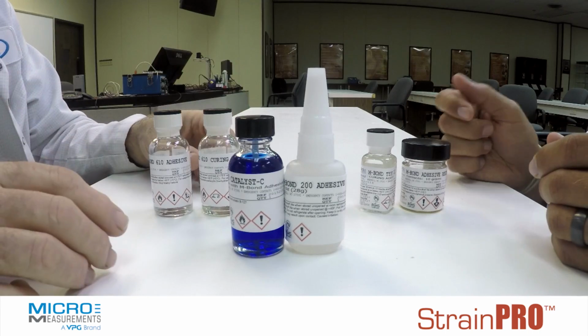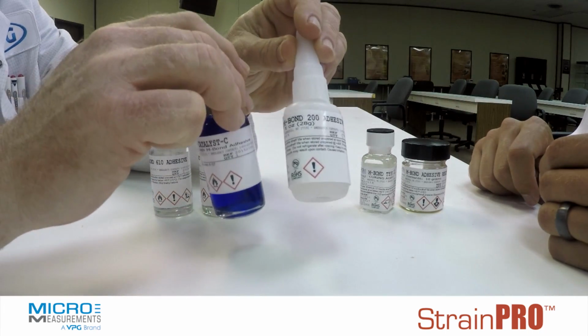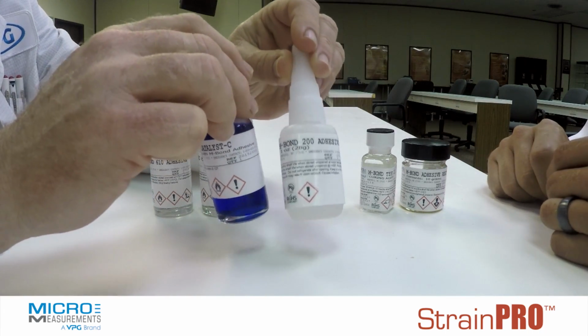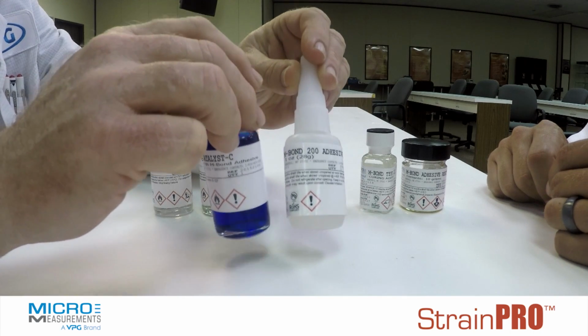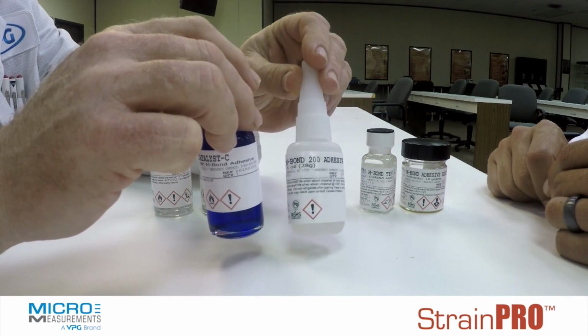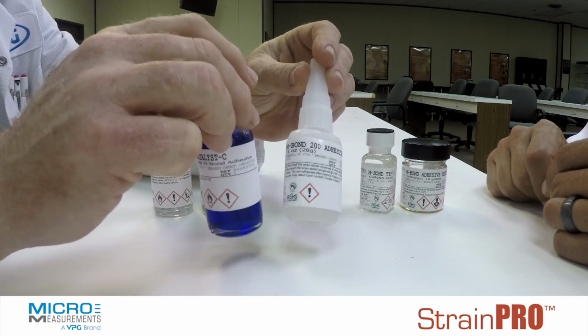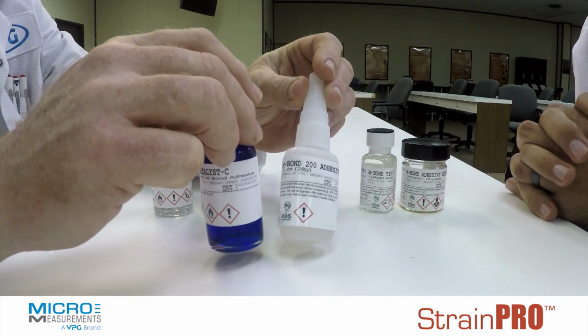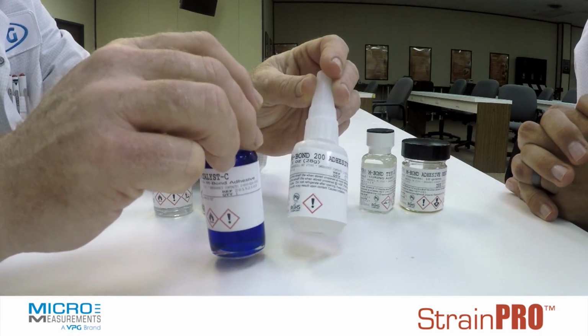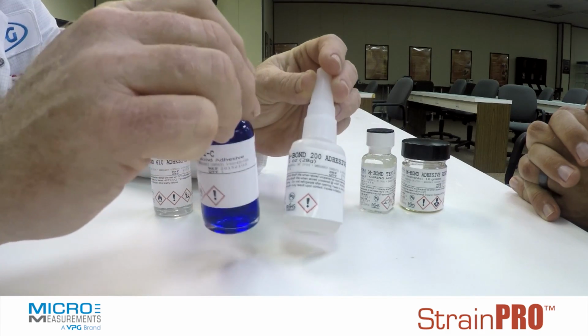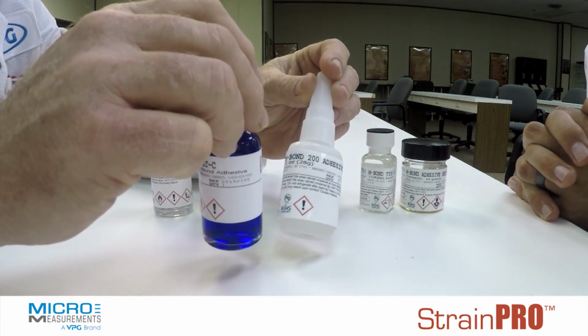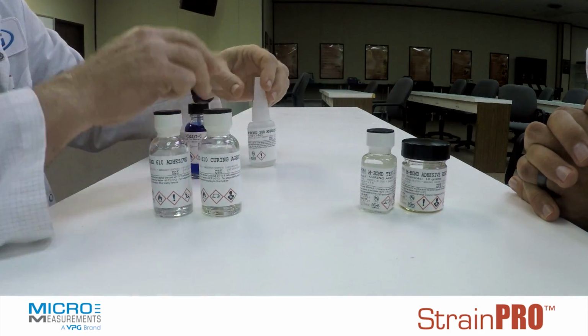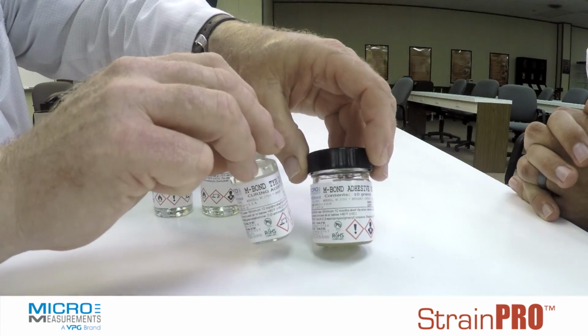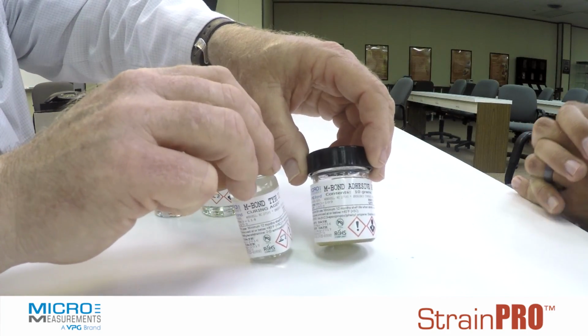Well, the first thing I would say is don't go to the hardware store and buy your adhesive system. You should buy a qualified strain gauge adhesive that has been tested and approved for that kind of application. But because of the porous nature of that fibrous material, the cyanoacrylate is absorbed into the surface and it starves the bond line, so it's not a very good choice. I would probably recommend something like our AE10 or GA2 or AE15.